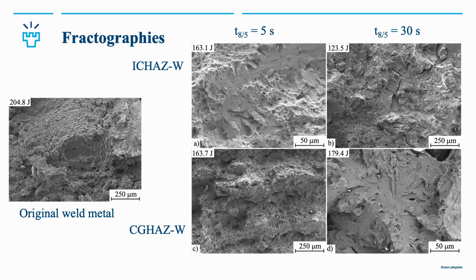And also, as in the previous image, we saw these quasi-ferrite regions in the intercritical heat affected zone with 30 seconds, and they are likely connected to these cleavage fracture areas, and you can see that also some cracks had started from these.